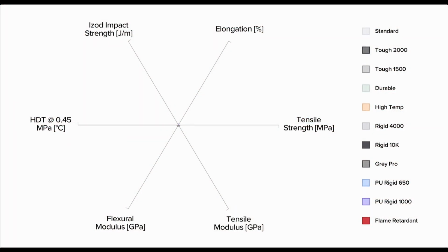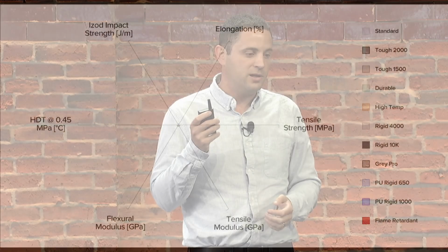So first up, everything we have today is a polymer. And polymers have a range of properties that go up to maybe 10 gigapascals in stiffness. There are totally other families of materials that can go way further than that. And in fact, we have one with a stiffness that's about 40 times higher, 380 gigapascals, just a completely different regime. And that is an alumina ceramic.